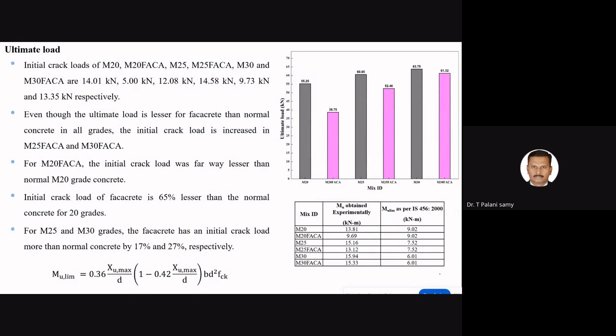Small variations are found between these two. This is the experimentally obtained value, and this is the IS 456 2000 value. Small variation happens due to some fixity of the specimen, and some constants we assumed in the calculation. So the ultimate load for M20, M25, M30, including FACA, is given here. You can get some idea.